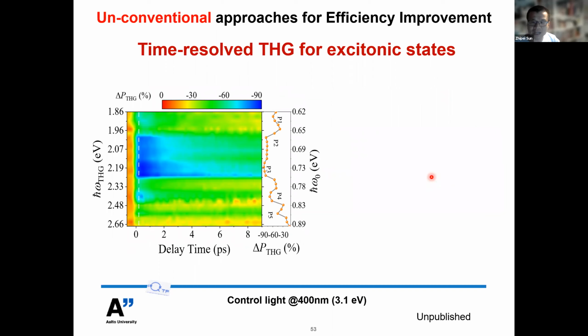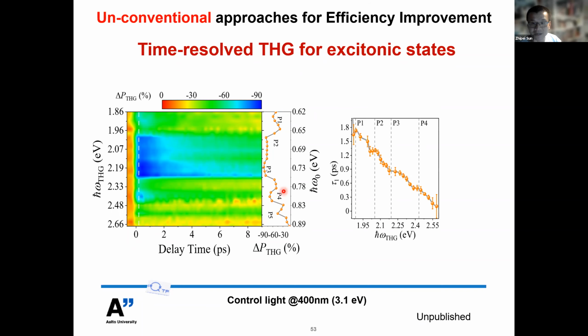We also did time-resolved third harmonic generation. We also found some similar results, and we found that the time-resolved third harmonic generation can also be a very useful method to probe the carrier dynamics. The results are shown here.